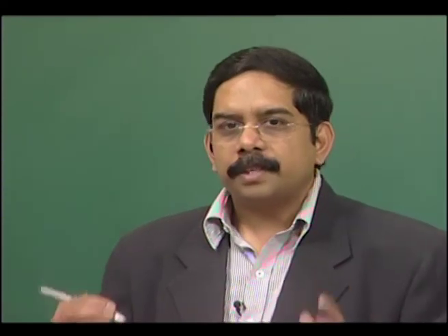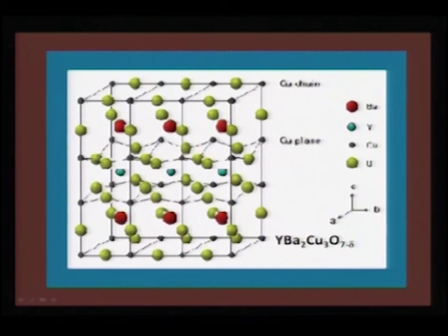Now, we will see more closely which of these oxygens are labile and how they control the superconductivity. This is one particular unit cell with the full composition of yttrium barium copper oxide, and in this you can easily observe these are the copper oxygen chains, and these are the copper oxygen planes, and their coordination actually is different here. But what you would see is that the high Tc is actually controlled by the copper oxygen chains, which are CuO4 type of units which are placed here. These copper oxygen chains are critical to the high Tc, and no matter what happens in the copper oxygen plane, it does not seem to adversely affect the high Tc. So, the core of the superconductivity is the issue of controlling the oxygen stoichiometry in the copper oxygen chains, because this is your AB plane.